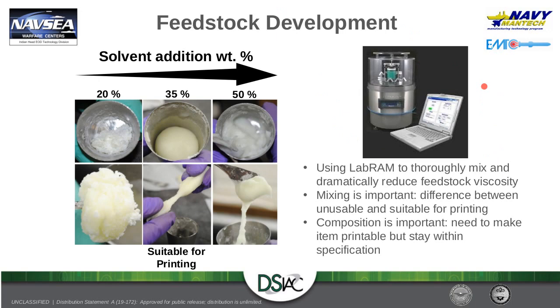What we went about doing with regard to our material is basically using a legacy fielded propellant that is typically processed in different means and mixed in different means, taking that wealth of information as per a recipe and translating that as a cycled, stepwise procedure with our LabRAM. So what you see here on the left-hand side is the study that we did with regard to producing a feedstock that might be amenable for our 3D printing process.